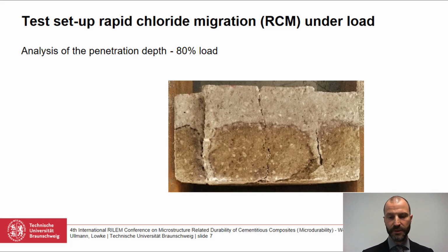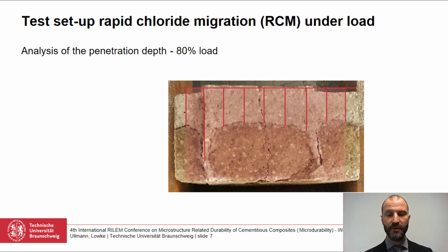When we take a look at this picture, we see the front of ingress of a specimen that was loaded with 80% of the ultimate load, and we see that at the edge regions 2 main cracks appeared, where the front of ingress was much higher than in the mid section of the specimen. If we depict the way of analysis that is proposed by RILEM, we can see that it is quite a coincidence if we can measure this mean depth of ingress or not. Maybe the point is just next to it.